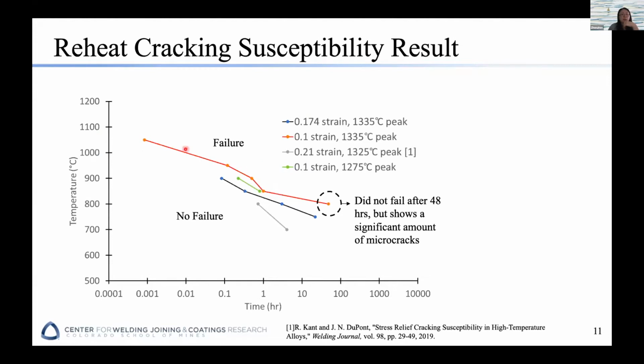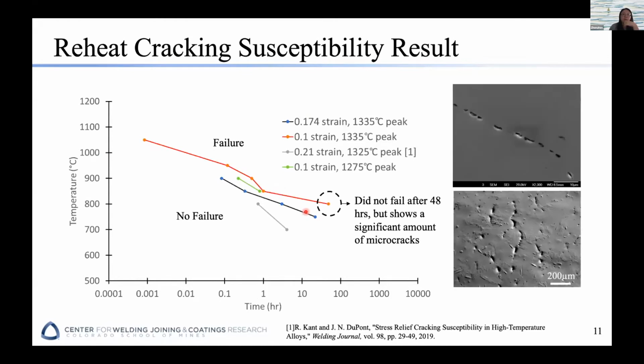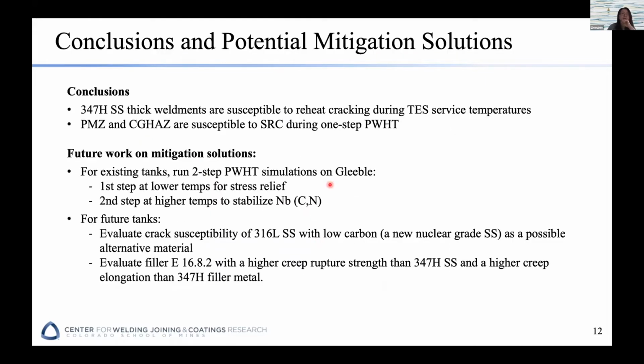Okay, so you can see at different amounts of pre-deformation and also at different testing temperatures, how much time it takes for the samples to fail. Okay, and even for the sample that did not fail at this point, you can see the cavity is already forming along the grain boundaries. So if we give it a longer time, it should fail eventually, okay? So this tells us if you don't do post-weld heat treatment, eventually at all sorts of temperatures, you're going to experience either a short life or a longer time before the component eventually fails, okay? So that's why we really need to provide a mitigation solution for this cracking susceptibility that we are expecting to occur in those 347 stainless steel thick welds, okay?